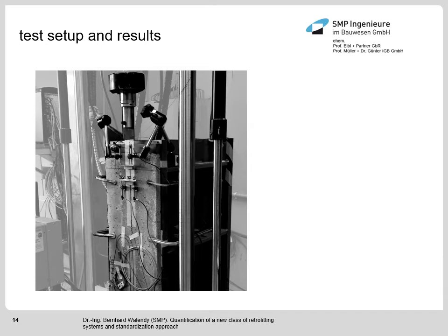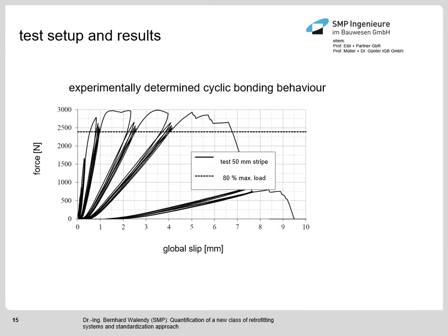Let's have a look at the results of a typical cyclic loaded test. This is a typical result from a cyclic loaded test. And as it is indicated here, we see the so-called global slip, that is the displacement at the beginning of the anchorage length, and the force. There are actually two things which I would like to stress. The first is we have very large displacements until decoupling or failure takes place, something between 5 to 7 millimeters until failure of the system occurs. That's the first point. And the second point is, as you can see here, we have very narrow hysteresis.